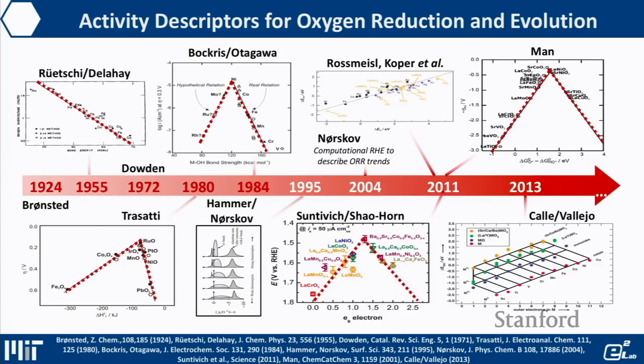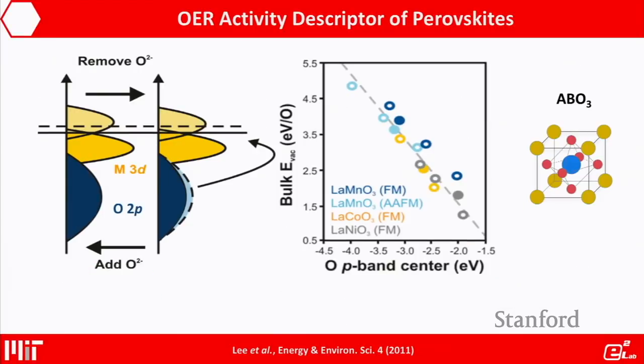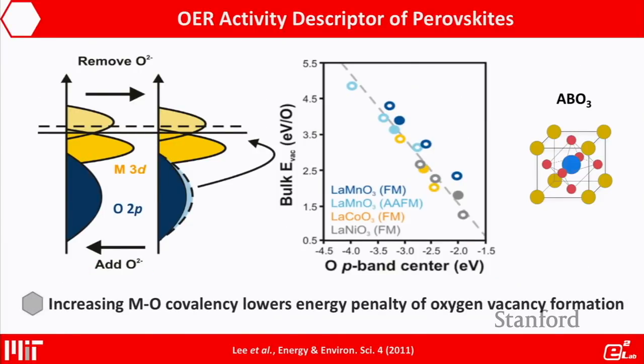So if we want to promote oxygen evolution reactions, we need to figure out how water would interact with the metal oxide surface, and what unique electronic structure features of metal oxides would dictate the turnover frequency of oxygen evolution. So I want to tell a story of perovskites, in particular how one can tune the metal-oxygen covalency as a way to control the oxygen evolution activity. For metal oxides, the electronic structure near the Fermi level typically has metal d states and oxygen 2p states. In a perovskite structure, we have the A site, the B site is a transition metal, and oxygen, O3.